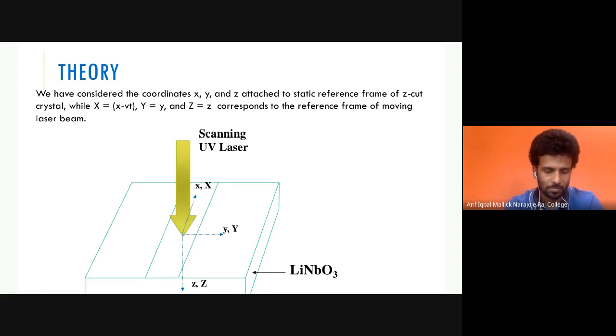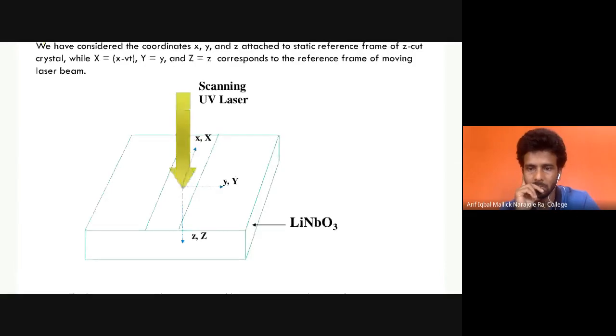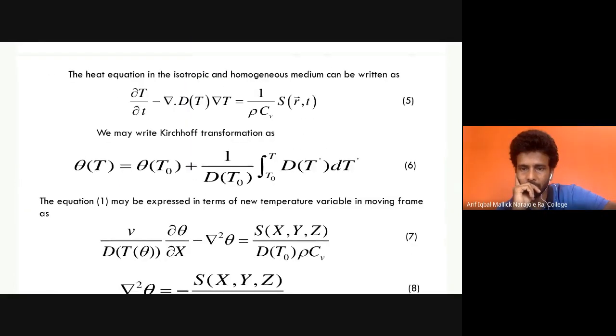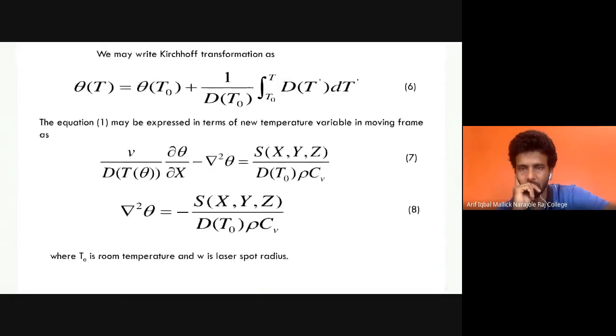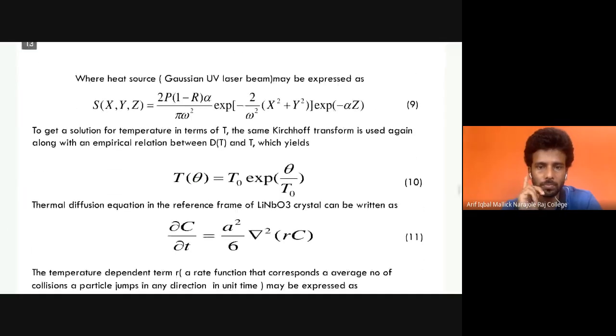There are two frames of reference: the scanning laser beam in the frame of reference capital X, capital Y, capital Z, and the fixed frame attached to the lithium niobate, expressed in small x, small y, small z. The heat equation is expressed in equation 5, where the thermal diffusivity depends on temperature. So the equation is non-linear, and to make it linear, we use the Kirchhoff transformation. Using it, we obtain equation 8, where S is the source term containing alpha. Alpha is the absorption coefficient.